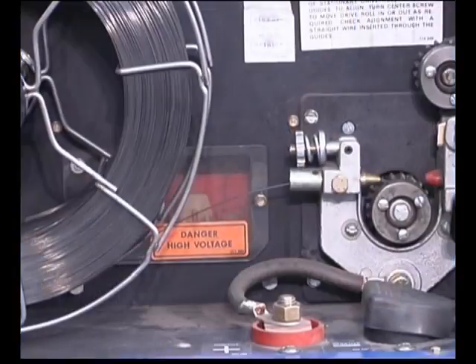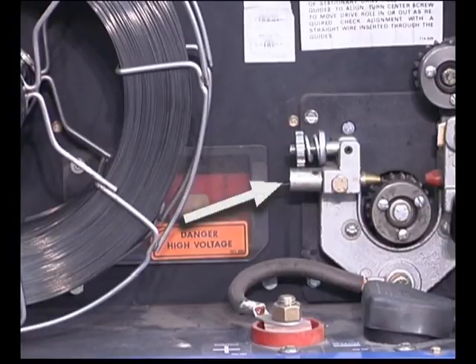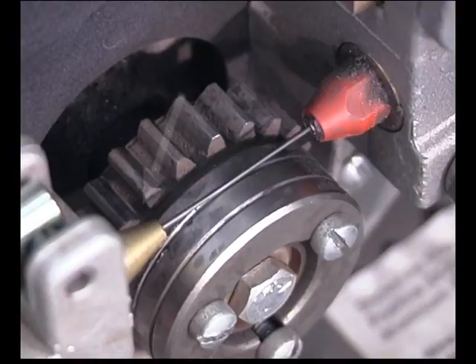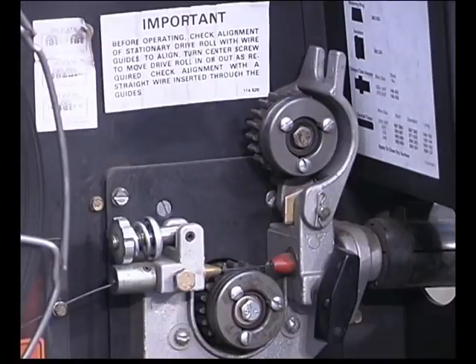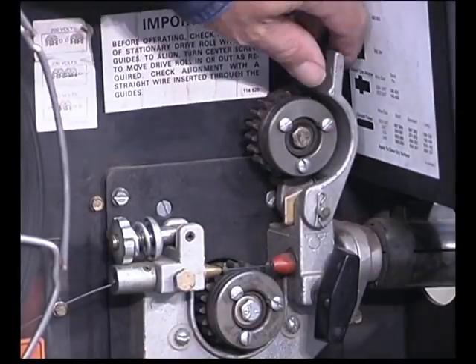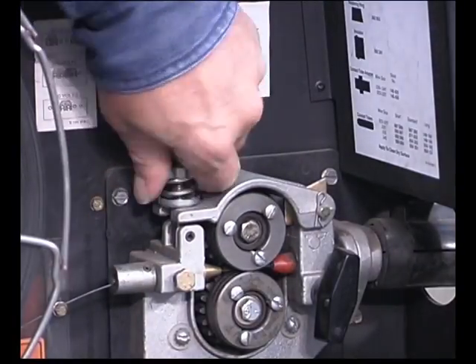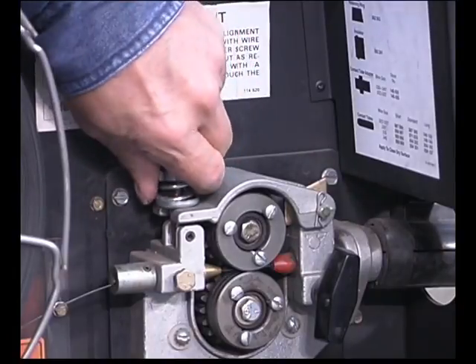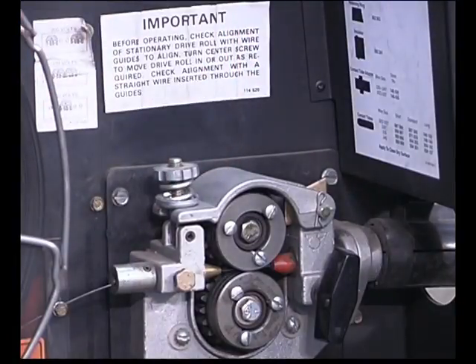To load the wire, mount the roll so the wire comes off relatively straight through a guide that keeps it centered in the groove on the drive rolls and into a steel liner inside the gun assembly. Before you close the drive rolls, make sure the wire is centered on the groove, then tighten just enough to keep the wire from slipping. Flux-cored wires, which are relatively soft, can be deformed if the drive rolls are over-tightened.